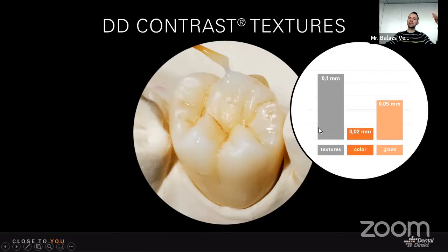As you see, the material thickness in the texture masses is a bit thicker. It means, and this is what you see here also in the picture, that with the texture masses you can build a minimal layer on a crown. Sometimes we see, especially with monolithic, full contour crowns, that after the sintering process, the technician or the dentist will figure out there are missing contact points, occlusal contacts, mesial, distal contacts are missing, and this is what you can do with the texture mass. You can apply it like a normal ceramic. It's a, let's say, micro ceramic material, and you can still create contact points with that, and the material is really stable, so you can place it really precisely on your surface.